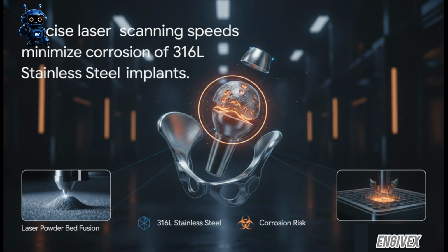But it's not just up in the sky, it's also going inside the human body. Medical implants rely heavily on 3D printed 316L stainless steel for things like bone replacements and even orthodontic brackets. Now this is fascinating. Research shows that if the precise laser scanning speed isn't absolutely perfect during printing, microscopic crevices and pores can form in the metal. In the highly corrosive environment of the human body, like when exposed to artificial saliva, these tiny pre-existing pores can actually accelerate corrosion, expanding to several times their original size. So quality control down to the micrometer is absolutely paramount here.